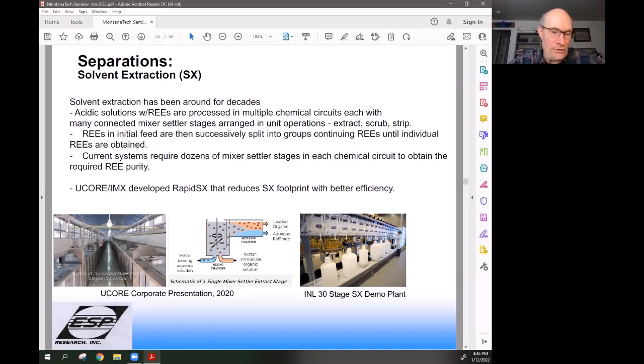Shown on the left side is the new upcoming UCOR facility located, I believe, in Ketchikan, Alaska, that is coming online to do these separations, and they're using 40 or 50 gallon tanks rather than 500 and 600 gallon tanks. And in the center of the diagram is what I've explained as the mixer settler concept, where you strip the metals out and get fairly high efficiency. So you extract the metal from the aqueous phase into the organic phase, you scrub it to be sure you've got as much as you can out, then you strip it out of the organic phase back into the aqueous phase using pH shifts.